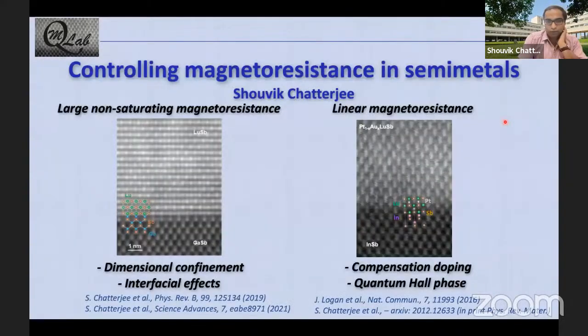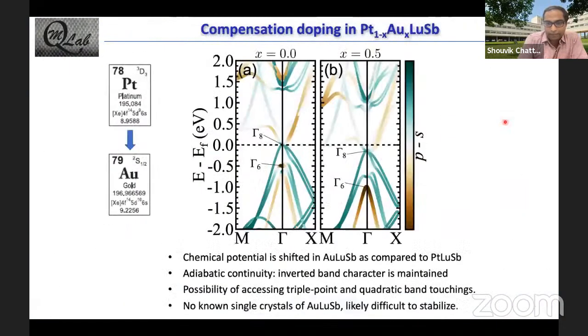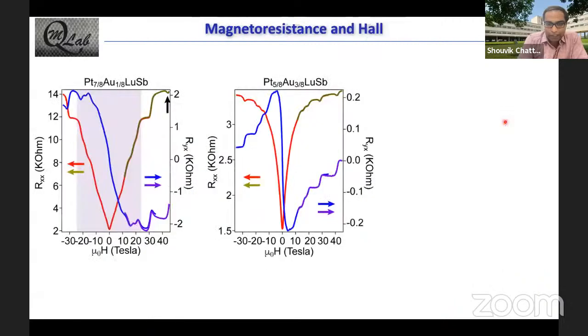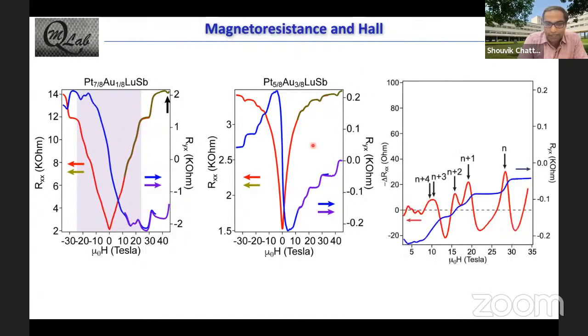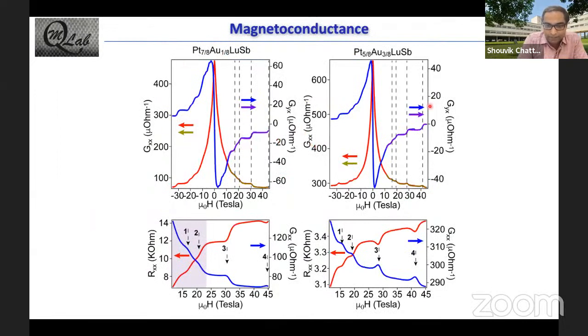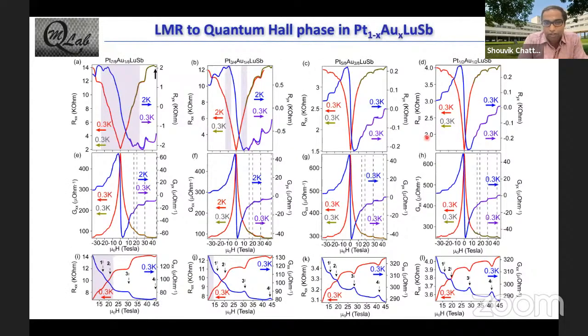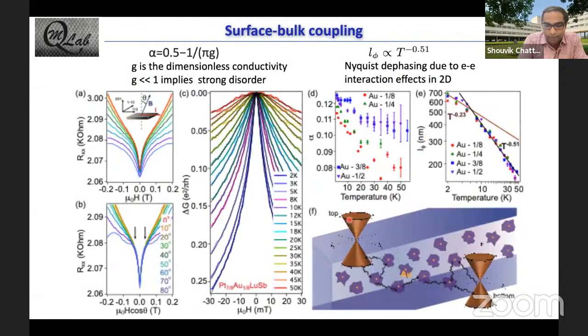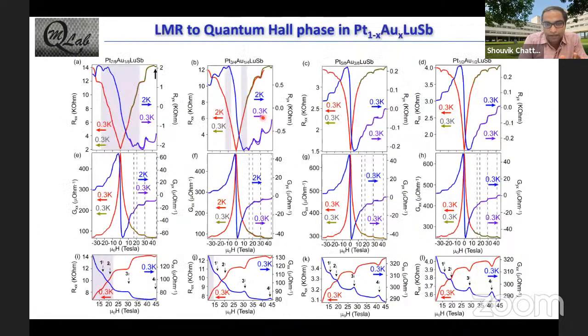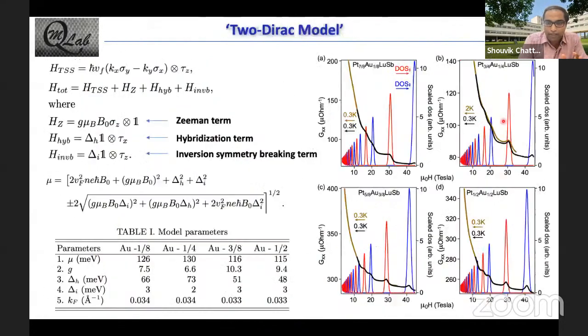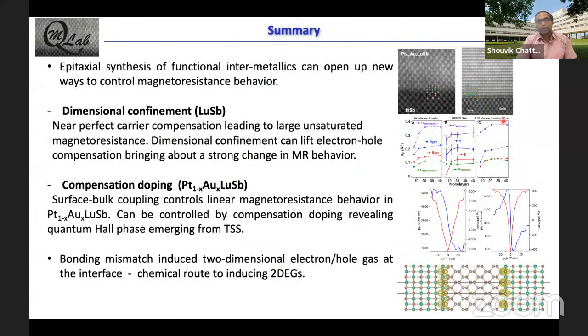Okay, I don't have much time, but I just wanted to show that in the platinum lutetium antimony system, just by changing the doping in this material, we can go from a very strongly linear magnetoresistance behavior to a phase which looks like a quantum Hall phase. And we can actually establish that this is coming from this. If you look at the conductance plot, this is actually very similar. And we could establish that this is all coming because of the tunability that we can have in the surface and the bulk coupling, that changes the behavior from this kind of linear magnetoresistance to this quantum Hall-like phase. With that, I'll just conclude.